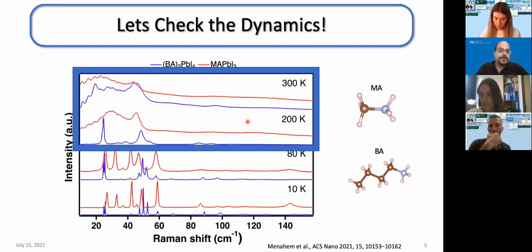Now, as we increase temperature to 200 and 300 Kelvin, we of course see redshifting and broadening of peaks as would be expected, but we also see dramatic changes in the Raman spectrum, indicating phase transitions.